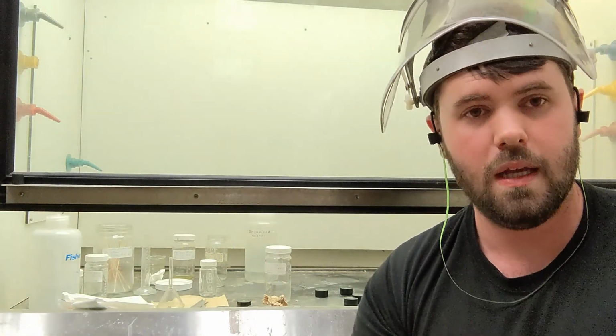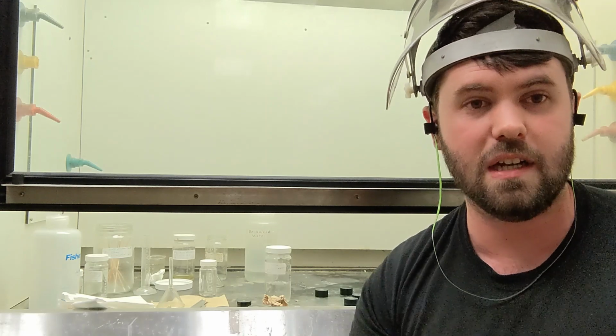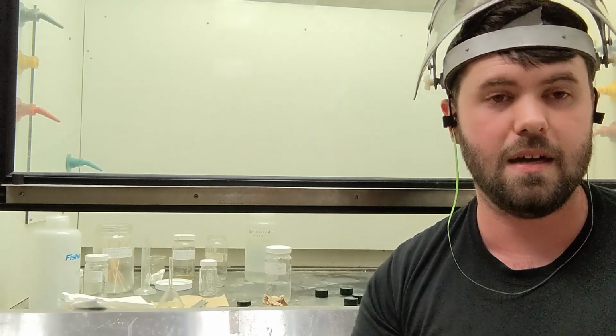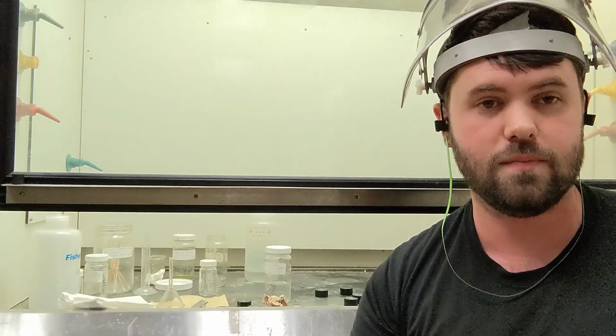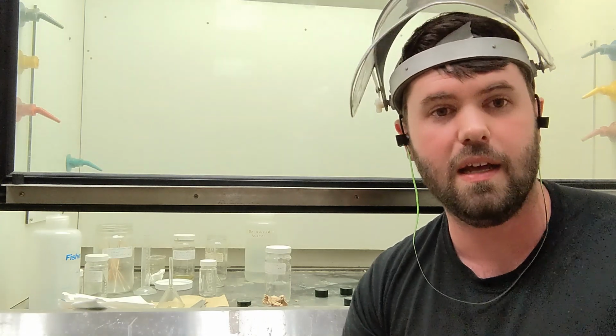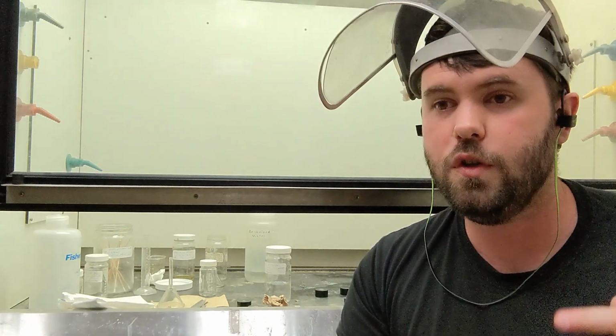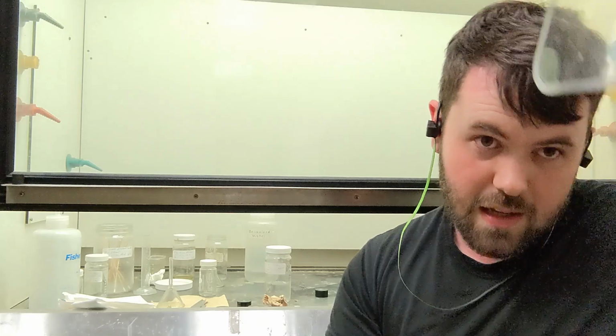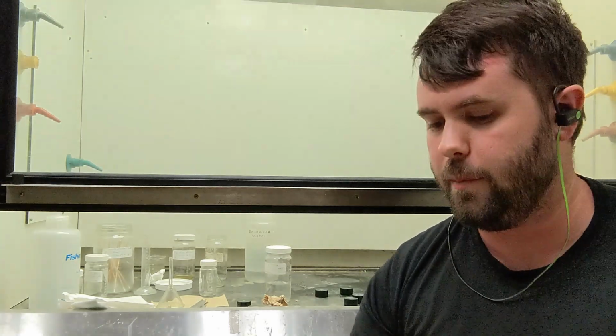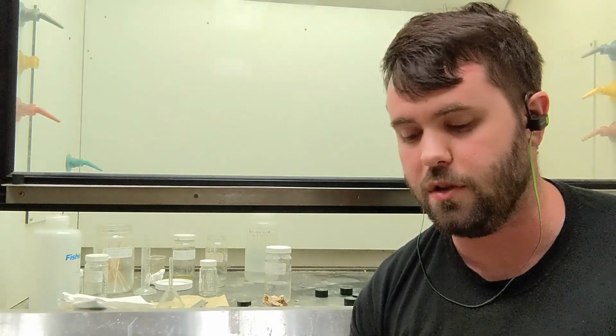Okay, so an important thing to do when you're new to etching is you etch for a short amount of time, and then we take it to the microscope and check. If you can see the grain boundaries, great. If you can't, you can re-etch for a little bit longer. Sometimes you can over-etch, which is kind of difficult to see if you don't know what you're looking at.